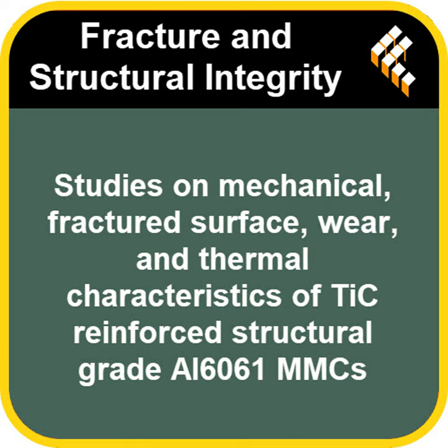Well, the reduction is attributed to a couple of factors. One is increased particle agglomeration. Basically, at higher concentrations, the particles start clumping together instead of staying nicely dispersed. Creating weak spots again. Exactly. And the other factor is increased brittleness. Too many hard particles can make the overall material less forgiving, more prone to cracking. This can lead to more voids and pores forming during solidification or under stress, ultimately weakening it. So yeah, too much of a good thing can in fact be detrimental. So the very thing that makes it stronger, the particles, can also become its weakness if overdone. It's that classic Goldilocks zone effect.